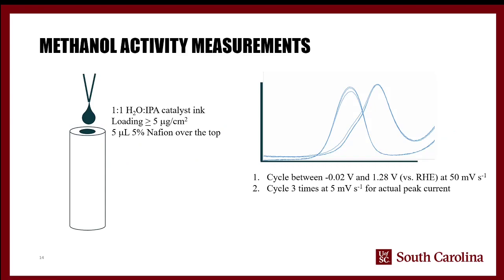So the next thing to do is basically do the methanol activity measurements. We've done our characterization. We have a range of metal ratios for both platinum nickel and platinum cobalt. And now we just need to go ahead and measure them and see what we actually get. The way we do this is take the catalyst, put it into 1-to-1 water IPA liquid, sonicate it to suspend the particles, and then drop a sufficient amount such that we have at least 5 micrograms per square centimeter of active area.